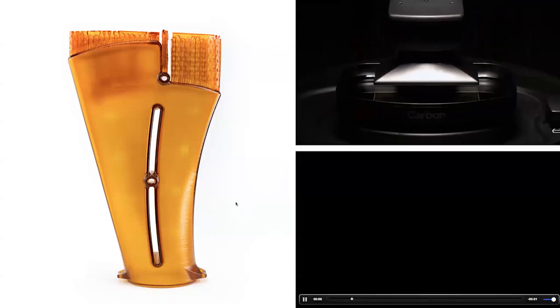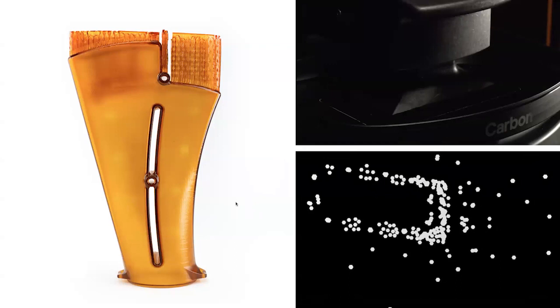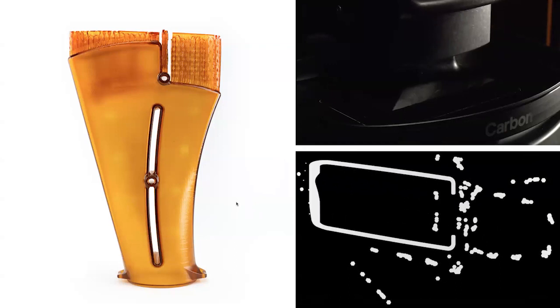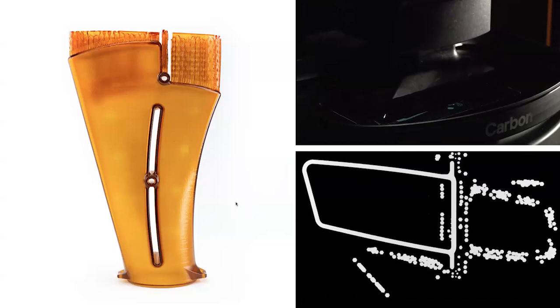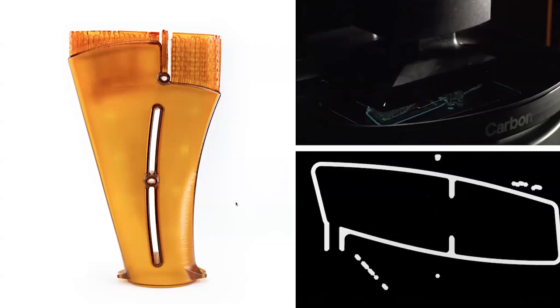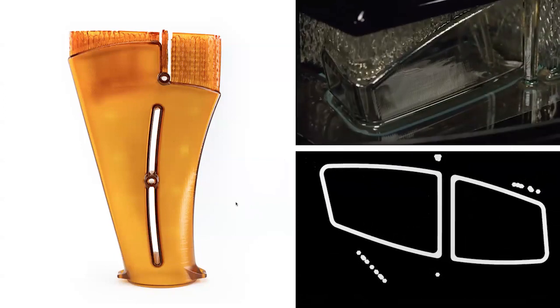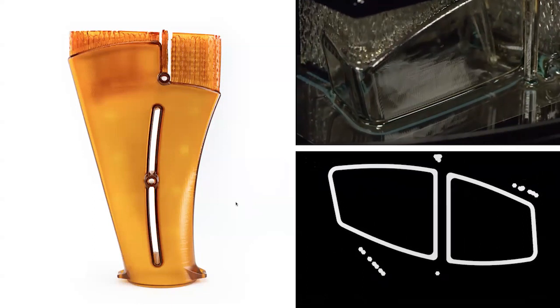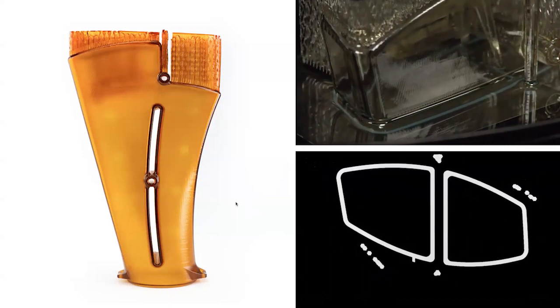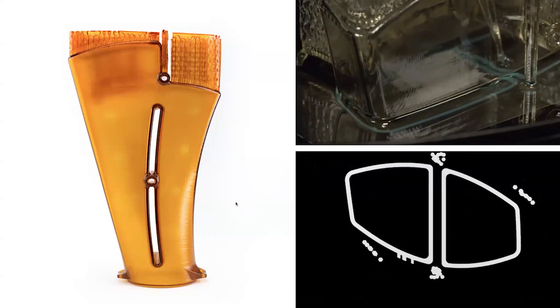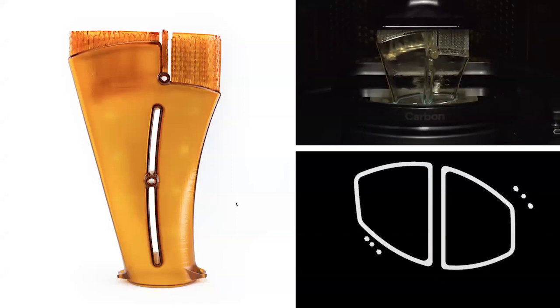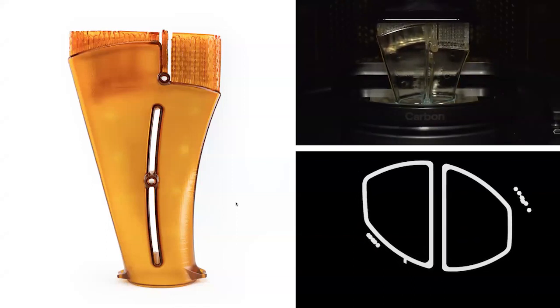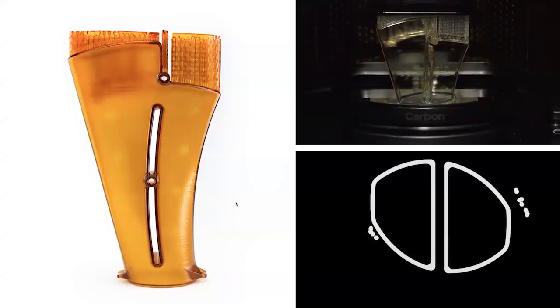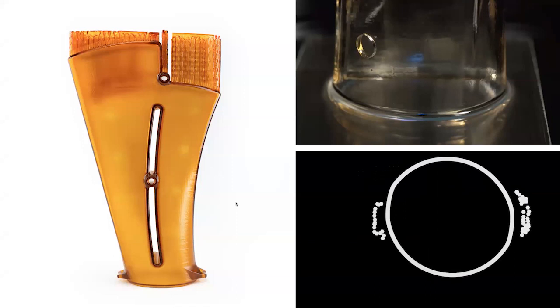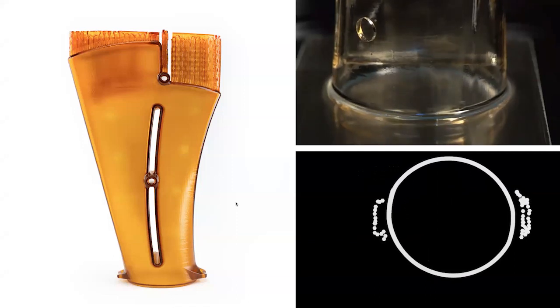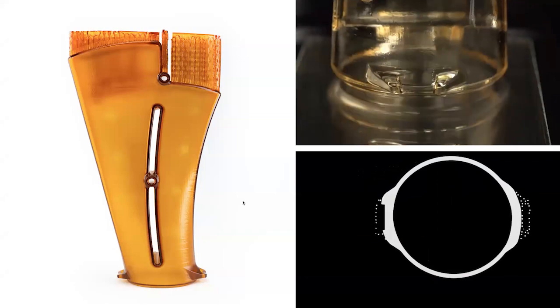You'll see this two-dimensional pattern of light get turned on here as soon as it gets close to the window. And then we're going to basically play a movie. And so this object is being lifted up off the window, but it's being done in a way that there's a gap between the growing part and the window. And that gap of liquid, the puddle, like the Terminator, is being sucked in underneath the part by suction forces as the object is being pulled up. And so the resin renewal, the flow of liquid into this gap, is the essence of this. And a gap provides the resin renewal for the growing object as things are taking off here.